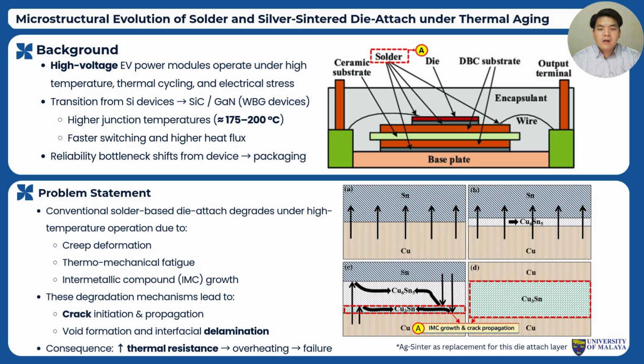So, what is failing? Conventional solder-based die-attach materials were originally developed for lower temperature silicon devices. Under the elevated operating conditions of EV power modules, these solder joints degrade due to creep deformation, thermomechanical fatigue, and especially intermetallic compound growth at the solder-copper interface. During thermal aging, brittle copper-tin IMC layers grow and promote cracks. This leads to crack initiation and propagation, followed by interfacial delamination, which disrupts heat flow, increases thermal resistance, and ultimately causes localized overheating and device failure.